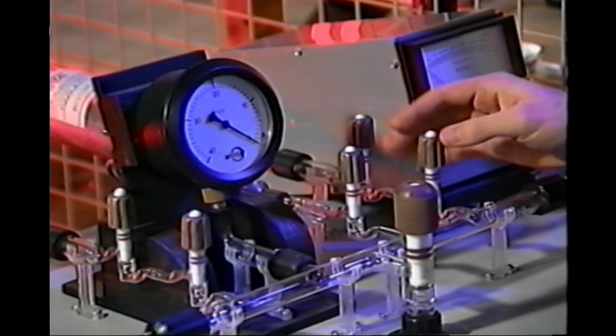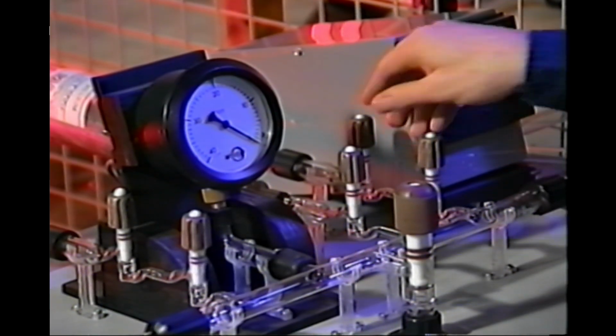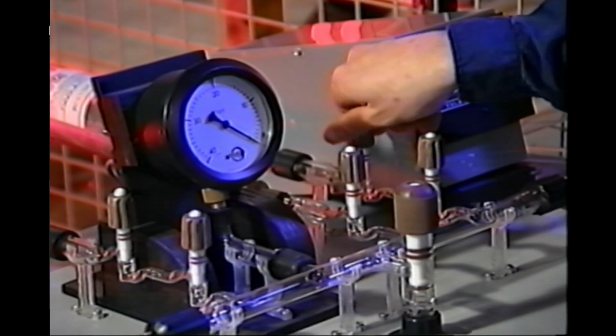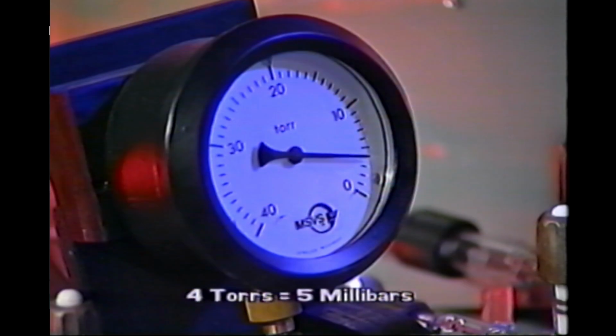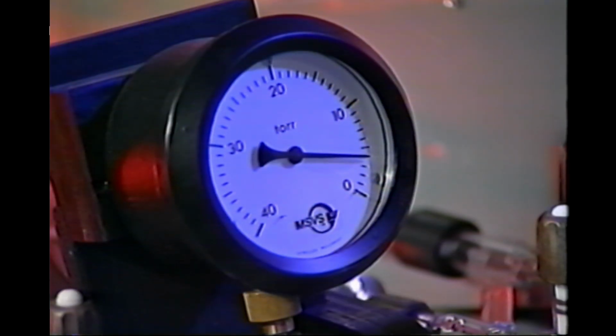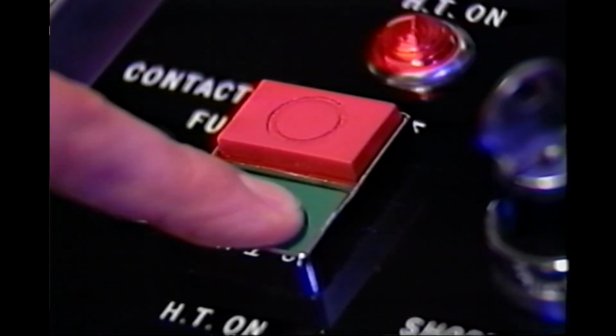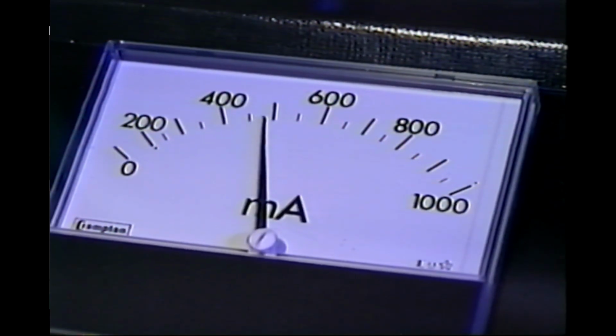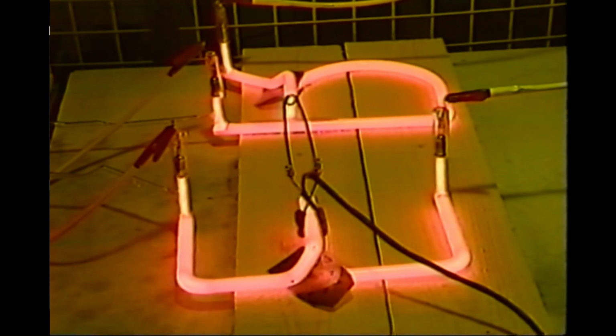After closing the helium stopcock, introduce helium gas into the tubes via alternate use of the stopcocks until a pressure of 4 torr registers on the capsule dial gauge. Switch on the current and increase to 500 milliamps. Allow the tubes to burn for 1 minute.